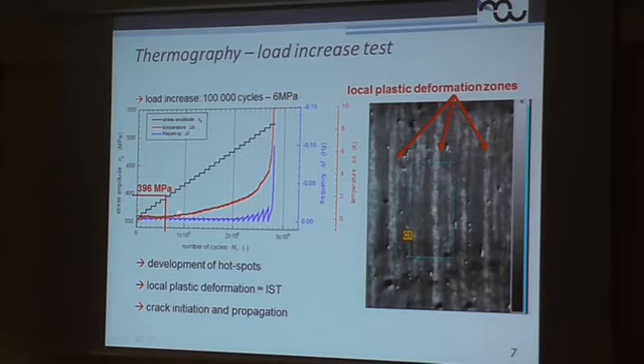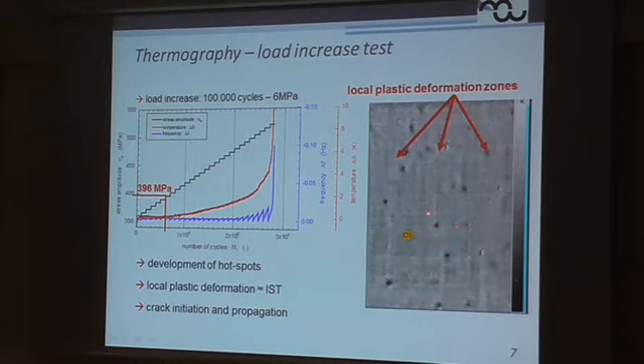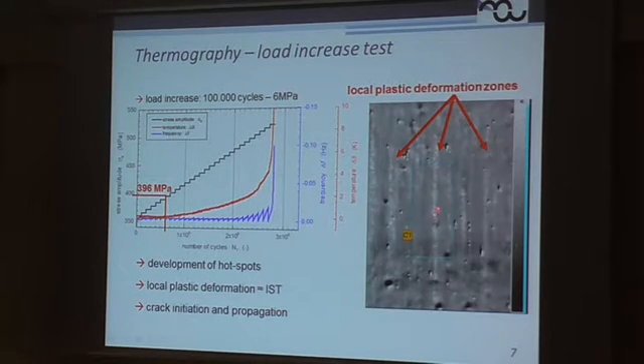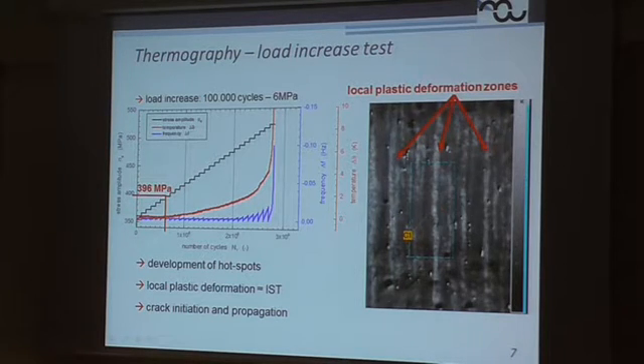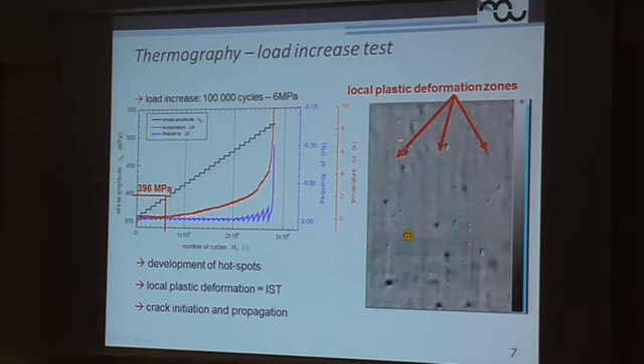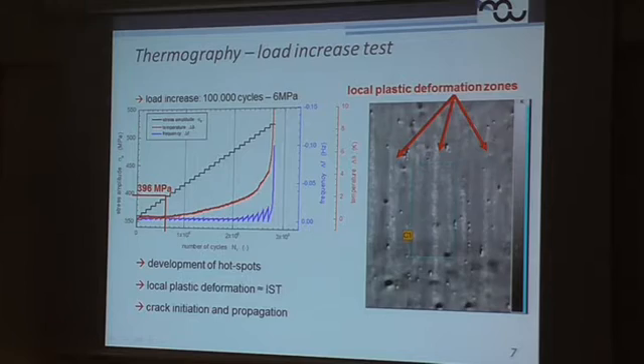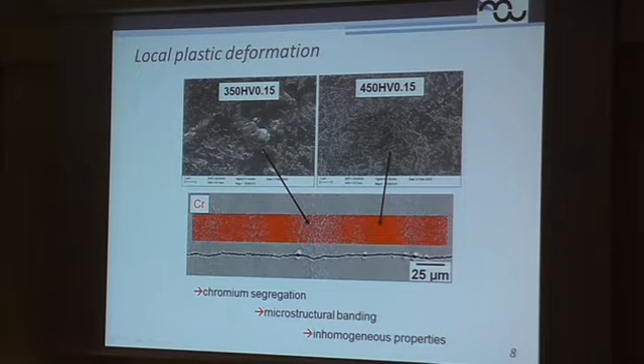This ongoing temperature change then correlates with the intensifying process of this local plastic deformation, and leads at the end of the lifetime of the specimen to a fatigue crack initiation and crack growth. What is interesting is that the local plastic deformation is located in these zones. And first we thought about something like a surface effect. So we were interested in what's really going on.